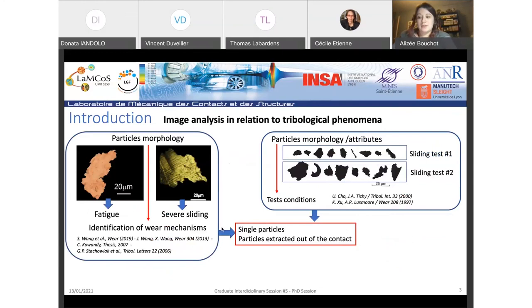The studies carried out to date have made it possible to link the morphology of third body particles to wear mechanism or to test conditions. They are always individual particles extracted from the contact by ferrography, and the particles in the contact, complex configurations such as agglomerates or their spatial distribution, are not taken into account.